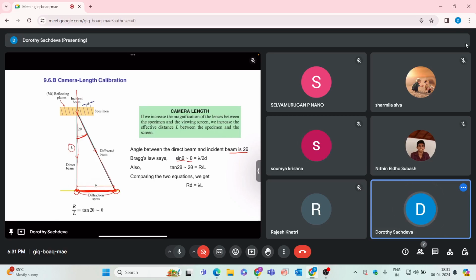So using this triangle and taking this as the angle 2 theta, the tan 2 theta value will be the perpendicular r divided by base L. So r divided by L will be equal to tan 2 theta. And since this is small, we can write tan 2 theta as 2 theta. And when we compare these two equations, that theta is equal to lambda by 2d and 2 theta is equal to r by L, on comparing these two equations, we get 2 theta equal to r by L, and from the other we can write 2 theta is equal to lambda by d. So comparing these two, we will get r by L is equal to lambda by d, or we can directly write Rd is equal to lambda L.